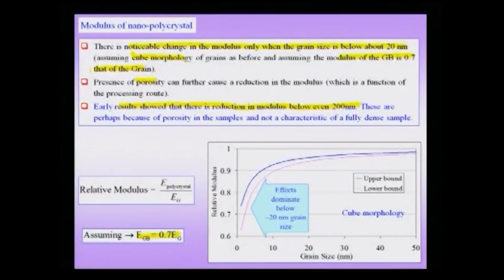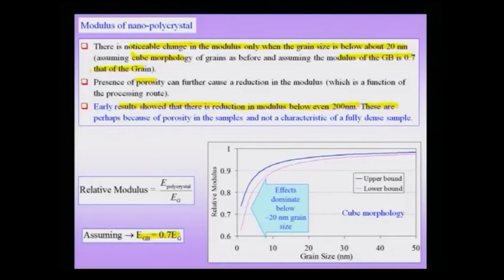And in fact, in the context of bulk modulus of a polycrystal, 200 nanometers can even be thought of as a bulk material. You can safely ignore most of the other entities in it, the other entities implying the grain boundary, the triple lines, etc. The result was perhaps because of porosity in the samples, and the investigators actually did not characterize a fully dense sample. So, we now can understand, perhaps in hindsight, that these were not really bulk, fully dense samples, and that was giving rise to the change in modulus below 200 nanometers.